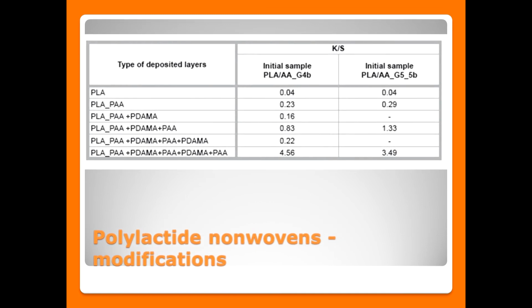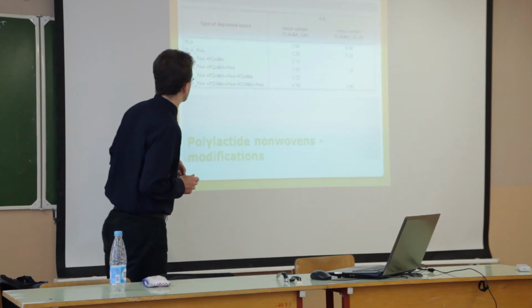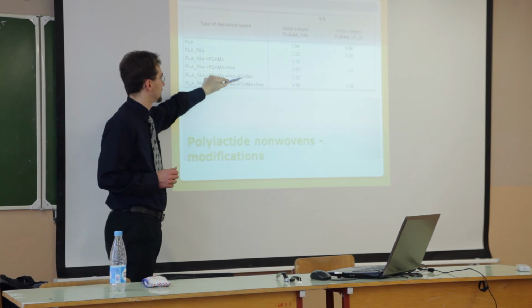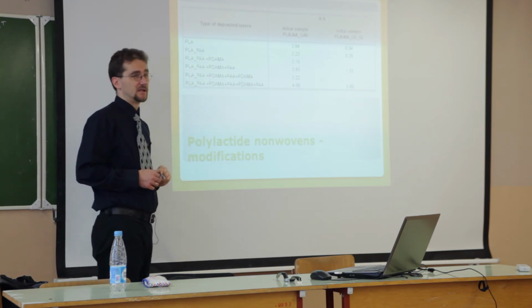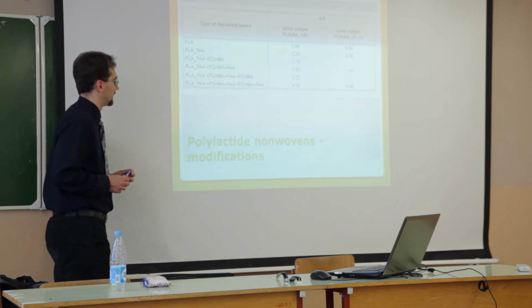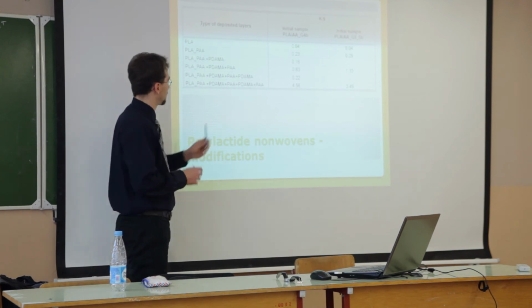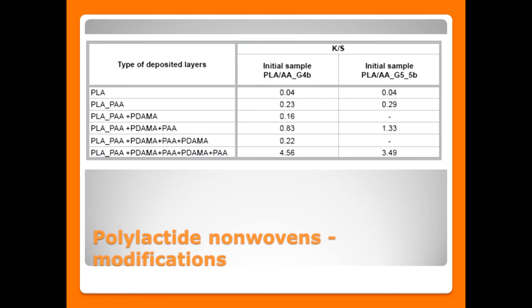And we received the multi-layered structure: unmodified, grafted with 2 layers, 3 layers, 4, and finally 5 layers. Of course, we have to remember that it must be on minus, on plus, on minus, on plus, on minus. It always must be oppositely charged. And we can see the changes in the structure, the colors.